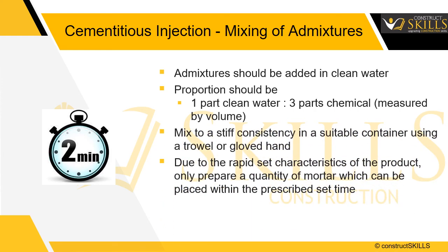Due to the rapid set characteristics of the product, prepare just a quantity of mortar which can be placed within the prescribed set time. The initial set time is approximately 1 to 2 minutes at 30 degrees Celsius.